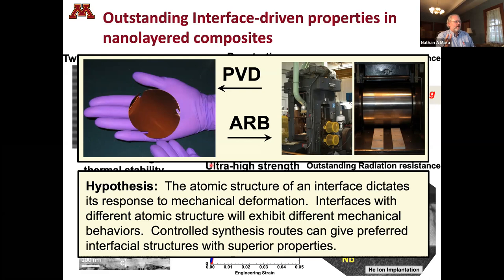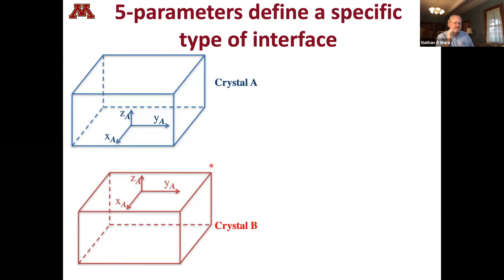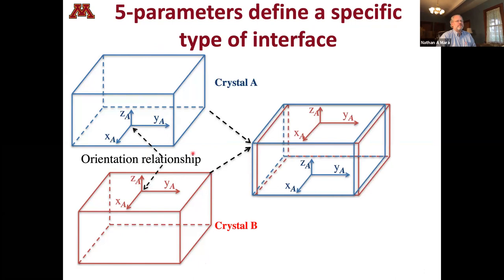So what do I mean by an interface? There are five parameters that define a specific type of interface when you're talking about crystalline materials. You've got crystal A, you've got crystal B. Three parameters define these axes and their relative orientation to one another. That's called your orientation relationship. But then you've got to figure out how to cut these things and put them together. And so what you do then is you have two more parameters that define the interface plane between them. And so that defines the entire geometry of that interface.